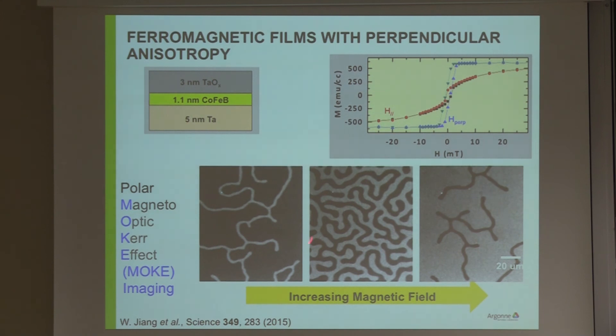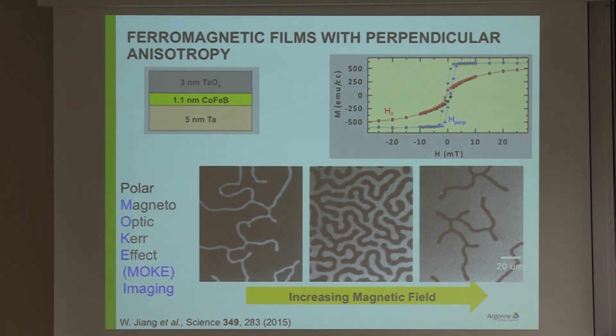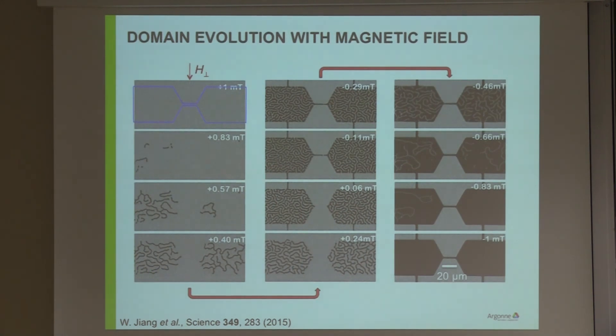If we look at the film and change the magnetic field, at high fields you still have a few stripe domains; when you saturate it everything goes gray, but at zero field you have, as expected for a very thin film, an equal balance of up and down magnetic domains. Kerr microscopy has about 250 nanometer spatial resolution, and these stripe domains here are about 5 microns. The sample I'll be discussing was a wire made from this film stack, but with the width reduced in the center by a factor of 20 — from 60 microns down to 3 microns — over a 20-micron length.